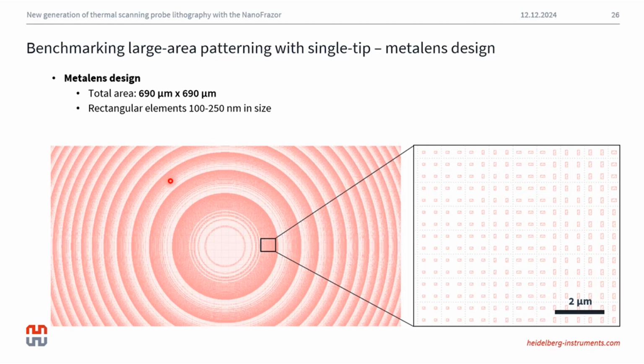You can see a glimpse of the MetaLens design here, and also a zoomed-in view of the smaller features that it's composed of. Here we're talking about rectangular elements that are medium resolution. They span between 100 and 250 nanometers in width, and they span a large area of about 700 by 700 micrometers. So in addition to patterning this large area metal lens with the heated tip, we also wanted to transfer this design and get close to creating a real functional device.